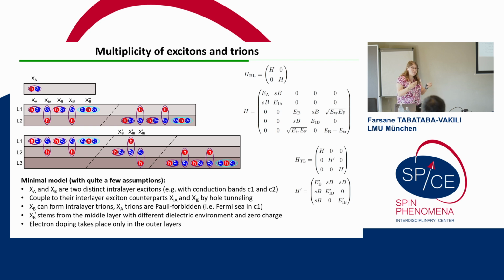Another indicator of there not being any C1 band is that we're not able to dope this XB prime. So it seems like the charge lives only in the outer layers. So we're only able to dope the first and the third layer.